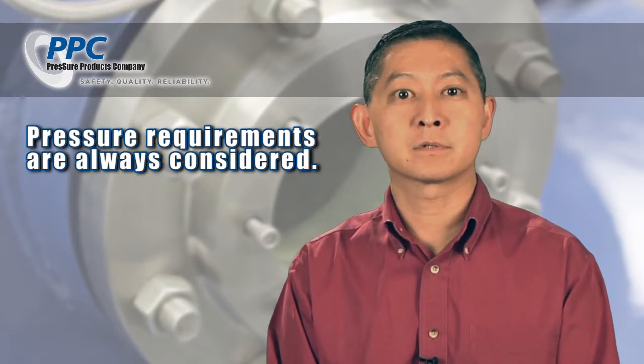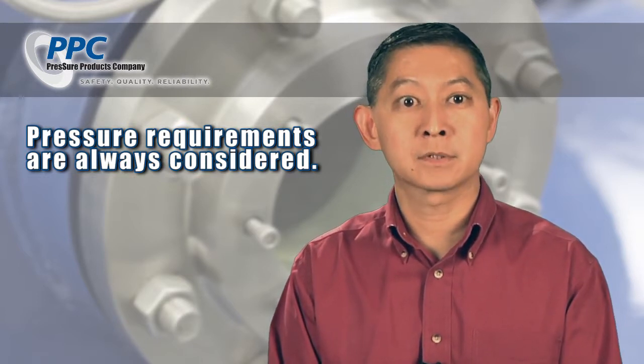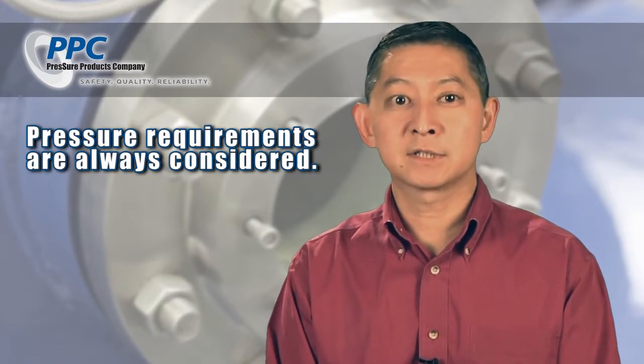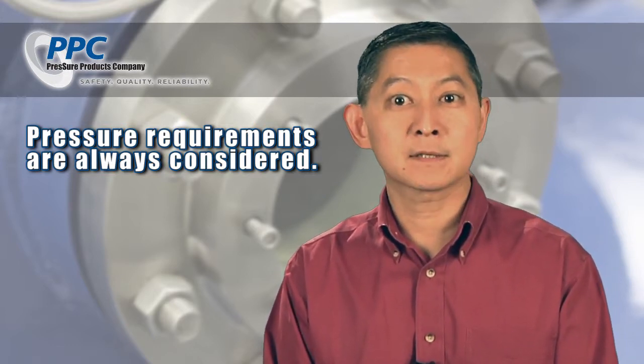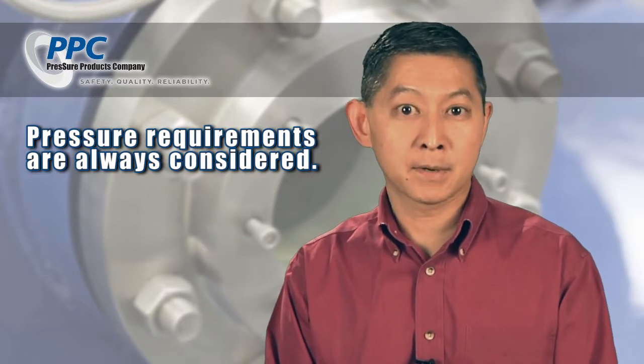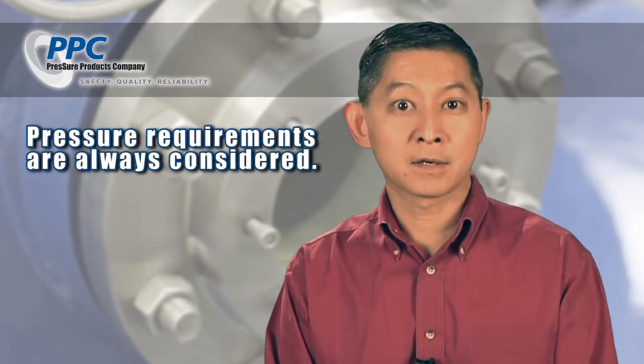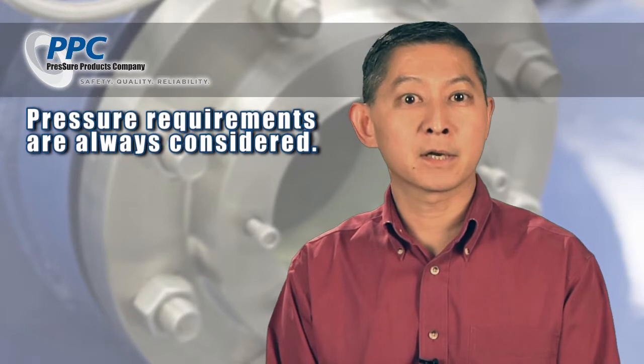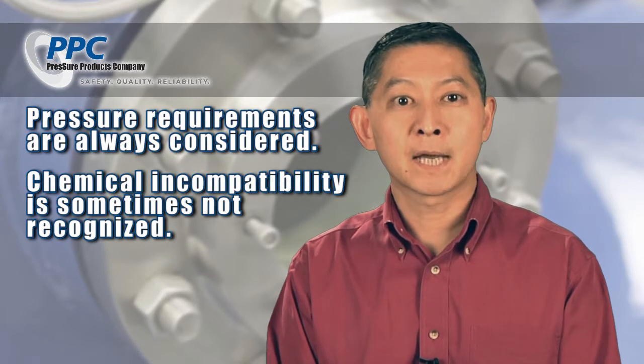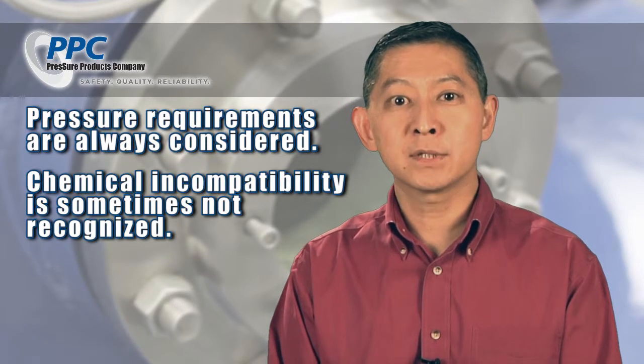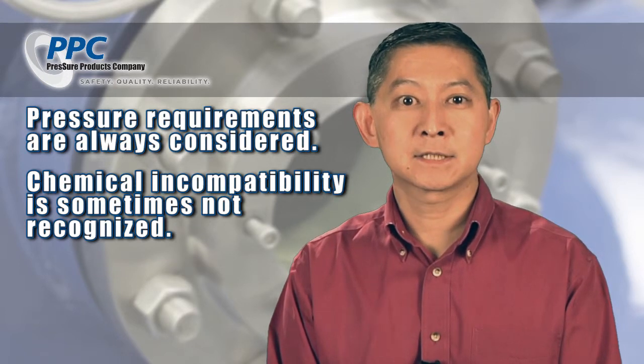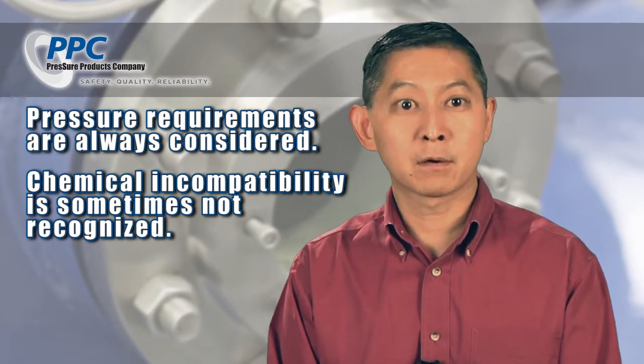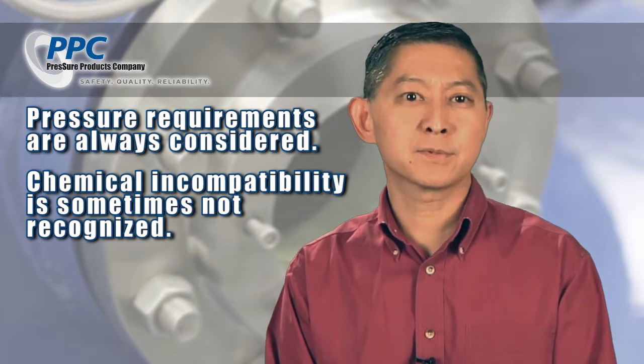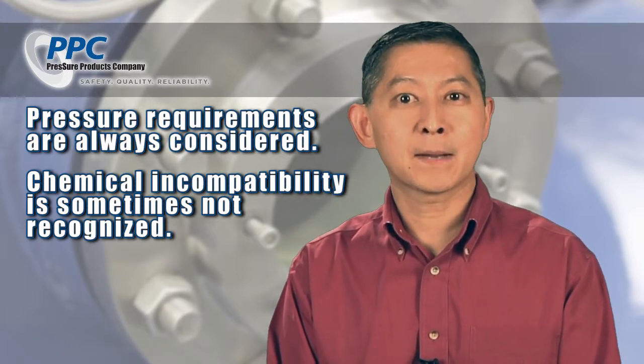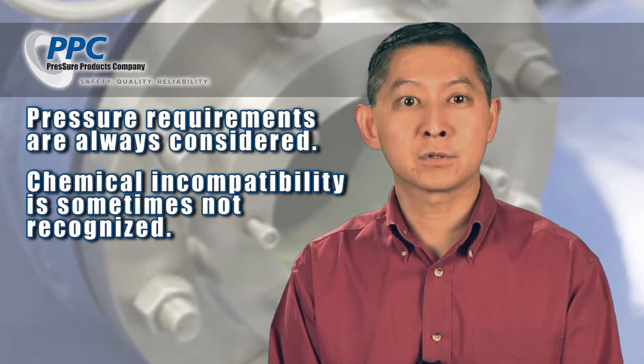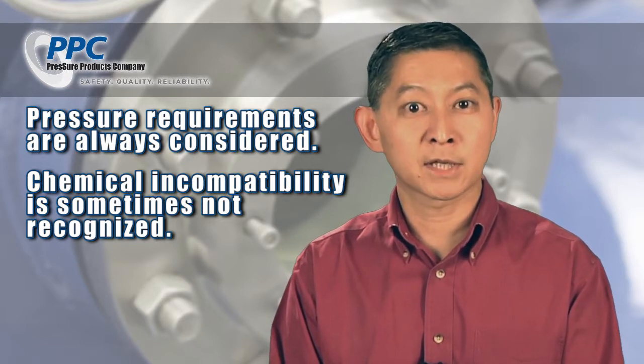Chemical corrosion failures are much more common than pressure-driven blowouts. In fact, I'll go so far as to say that chemical corrosion has ruined more sight glasses than all other failure modes combined. And the reason is that, unlike pressure, most people don't think about it before specifying a sight window. What exacerbates the issue is that window materials, plastic and glass, are both commonly considered to be corrosion resistant. But nothing is resistant to everything, so for any given application, it's very important to make sure that window is not reactive towards the process fluid.